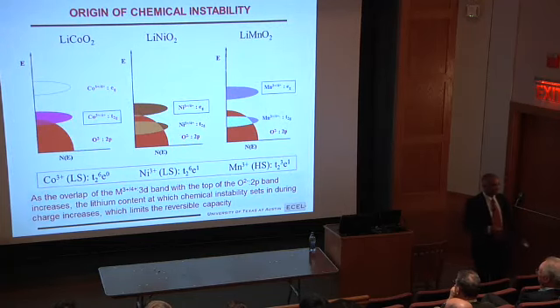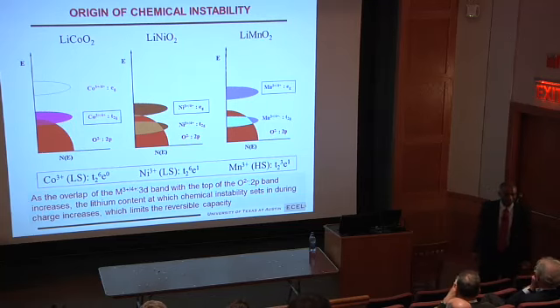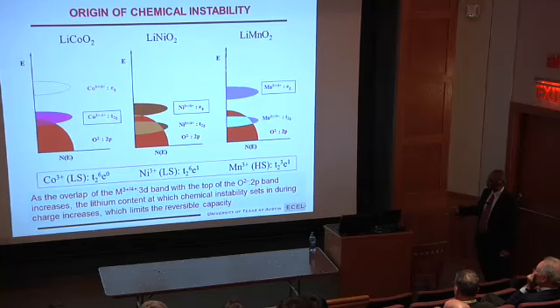Okay. So safety-wise, cobalt is the worst actor. If you go to nickel, for example, it has one more electron. So instead of, I think this is a lot of chemistry I have to teach, crystal field splitting, I'm not going to do that. This is a little bit above, so safety-wise it's better. Manganese is really the best one because the manganese redox active band is well above the top of oxygen 2p.